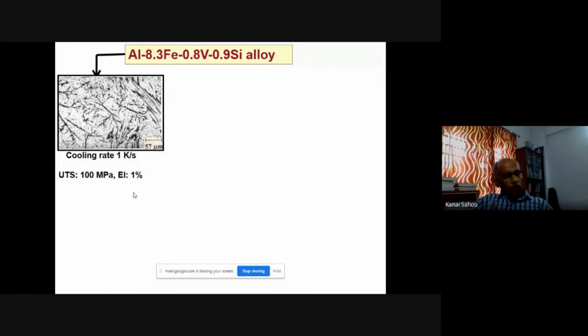For example, I have taken one example of how to modify the structure. Very interesting example. It's my own work, my doctorate PhD work. It's a long time back. So here, if you take aluminum, 8% iron, vanadium, silicon alloy, this alloy is used for, say, rapid solidification technology. So can you imagine, the structure is very coarse, highly elongated structure, all these dendrites, all this elongated structure, so no use, very poor properties.